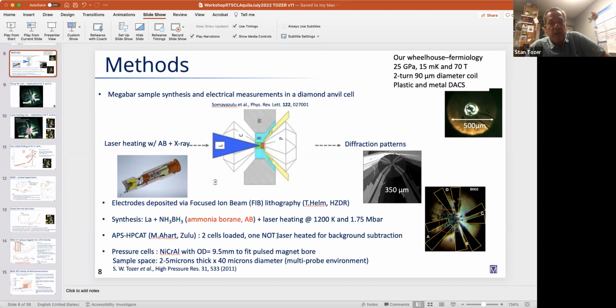when Audrey tried to laser synthesize that material, we saw a bright flash, and Ravi told us we needed to stop because most likely it broke. That was an indication that we had broken the diamonds. It was the best thing that we could have done because that gives us our control cell, and that cell is B003. The cell that made this superhydride is B002, and I'll refer to them that way in the talk.